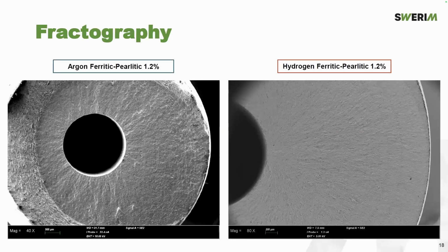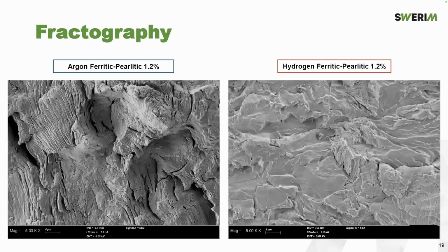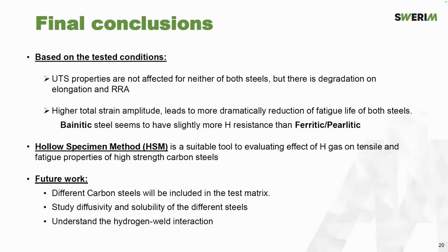And this is a fractography. If we compare this in hydrogen and this in argon, it's possible to see some kind of bands of crack propagation. And this is a higher magnification. You can see a ductile failure and some quasi-brittle features.